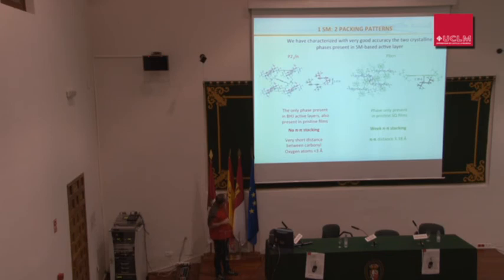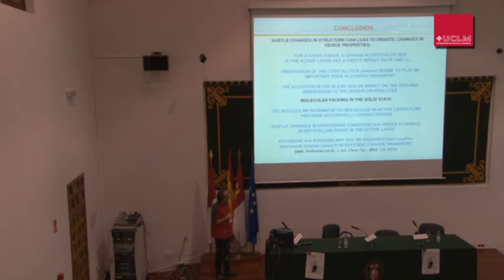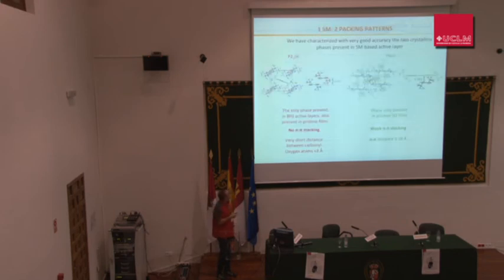So we have no pi-pi stacking at all, and we have this structure which is the predominant one in very efficient devices. So we told this to the guy that published the paper on the squaraine, the 5%, and the guy said, oh, this is wrong, because we have always seen this. But that's because they always crystallize films without the PCBM or without the fullerene, which makes no sense because you have this molecule when you make the device. So you have to always work in the real conditions. Ideal conditions are nice and easy to understand, but it's not the real world.